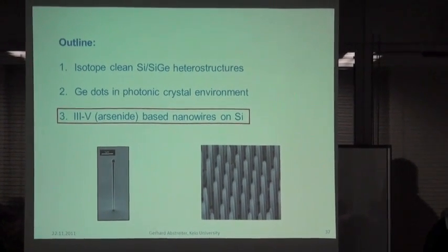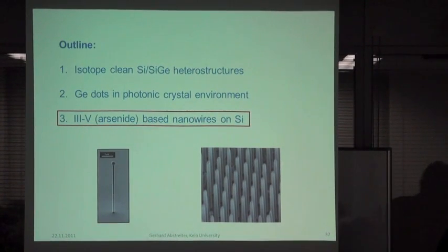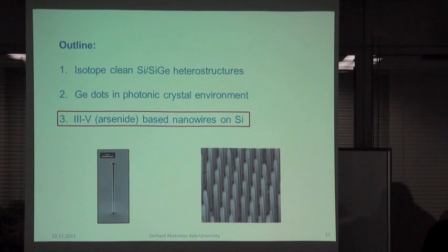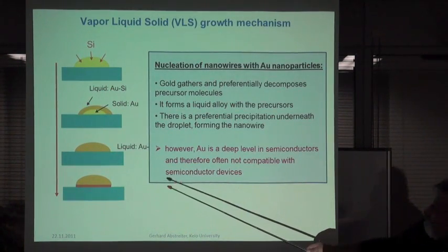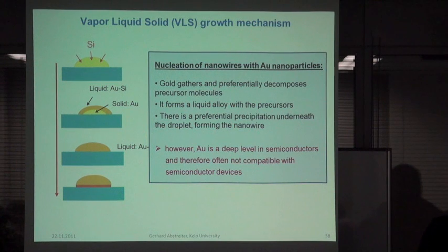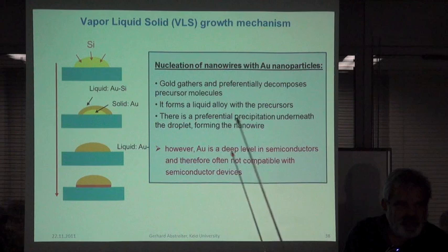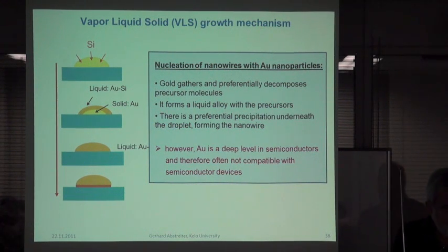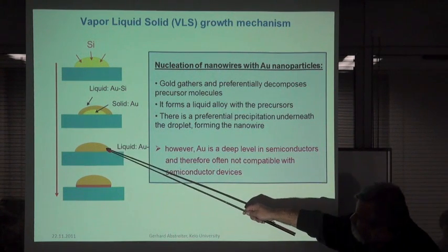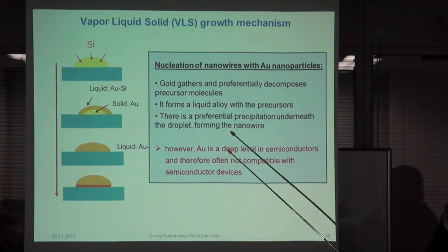Nanowires are grown normally with an external catalyst. People are using gold, and this is an old story. I mean, the first growth of silicon with gold was in the end of the 50s by Wagner and Ellis. Actually, it's interesting, their paper was not cited too often, over 40 years. And since now 10 years, it's cited 400 to 500 times per year. So it has now, in the last 10 years, got more than 3,000 citations because they sort of had the first paper on vapor liquid solid growth, how it's called.